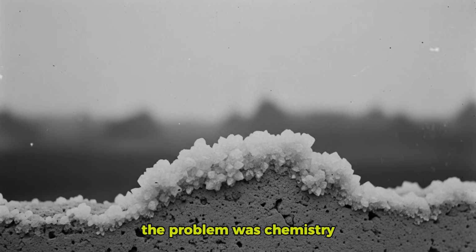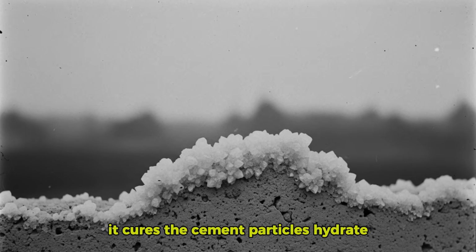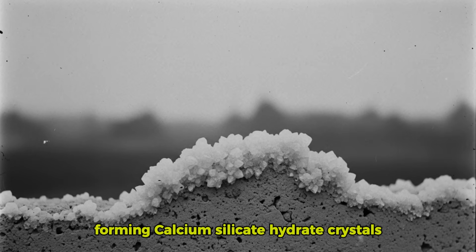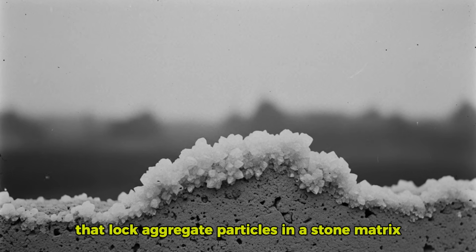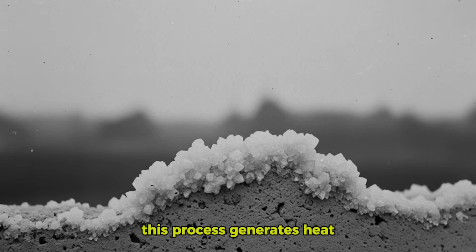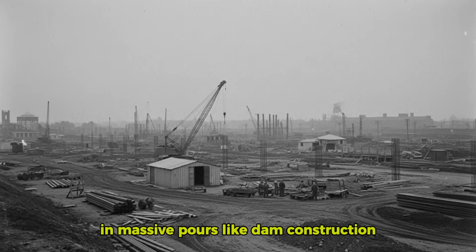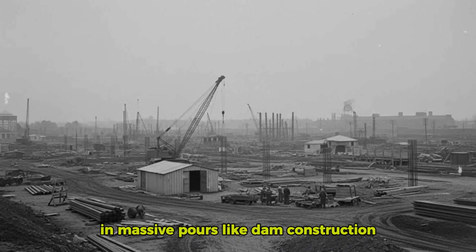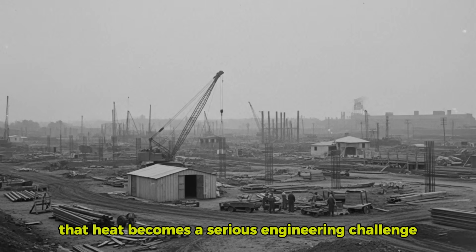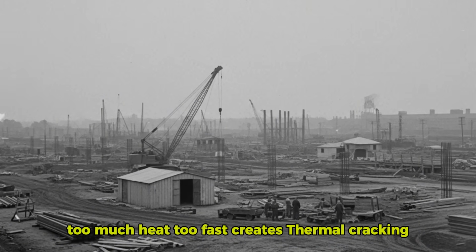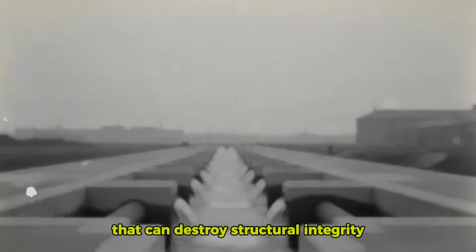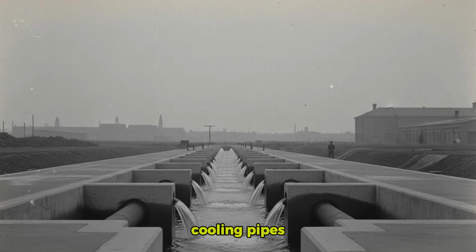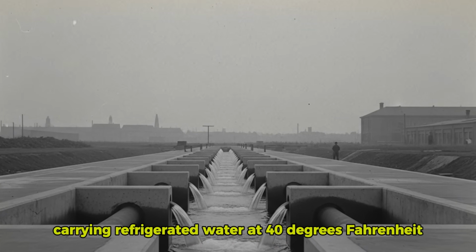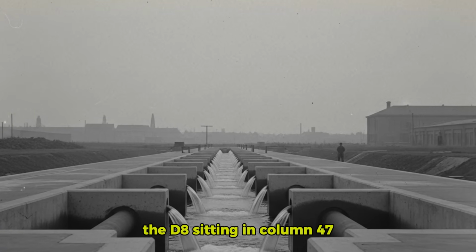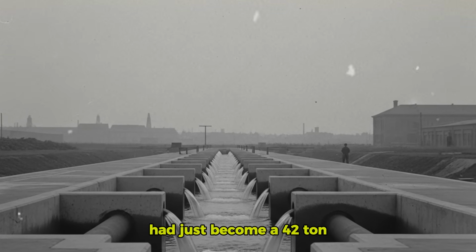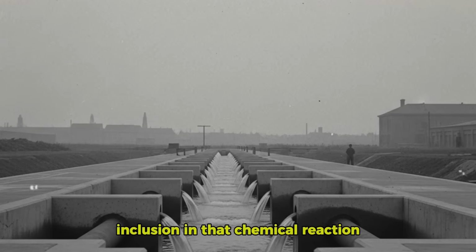The problem was chemistry. Concrete doesn't dry, it cures. The cement particles hydrate, forming calcium silicate hydrate crystals that lock aggregate particles in a stone matrix. This process generates heat. In massive pours like dam construction, that heat becomes a serious engineering challenge. Too much heat too fast creates thermal cracking that can destroy structural integrity. That's why Hoover's concrete contained embedded cooling pipes carrying refrigerated water at 40 degrees Fahrenheit. The D8, sitting in column 47, had just become a 42-ton inclusion in that chemical reaction.